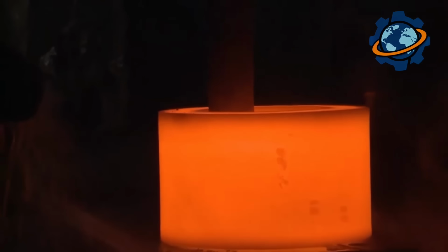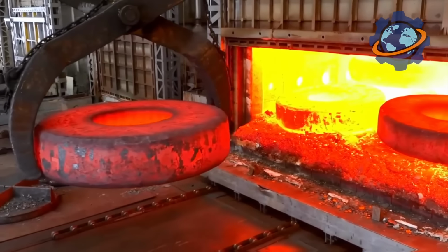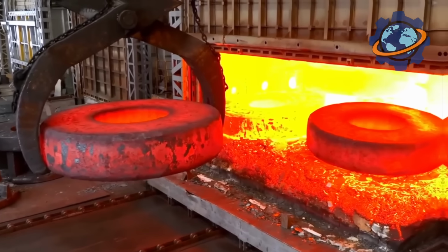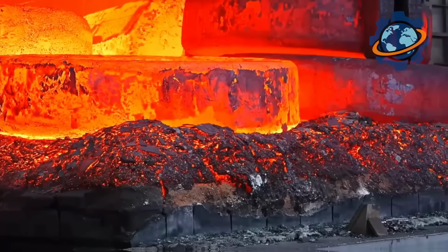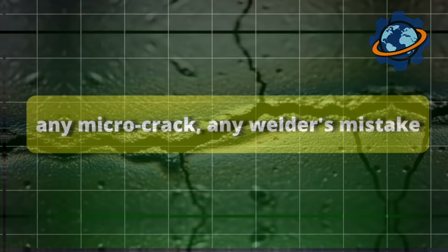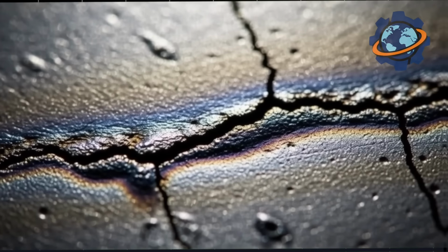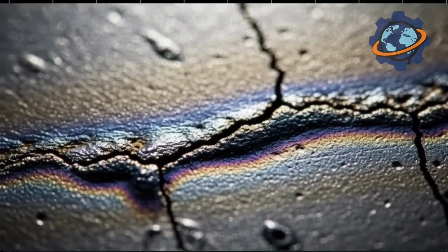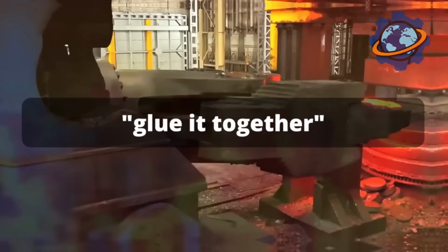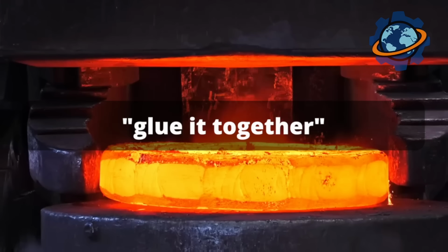In the past, rings this size were made by welding together several large segments. Looked good, but those longitudinal seams always carried a hidden risk. Any micro crack, any welder's mistake, and during an earthquake or under long-term loads, that seam could become the weak point. Chinese metallurgists decided to go a different route. Don't glue it together, grow the ring from a single piece.